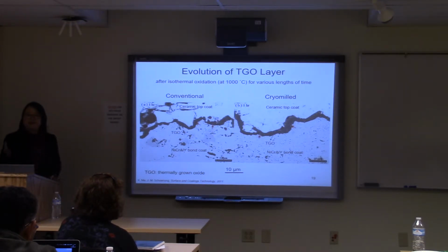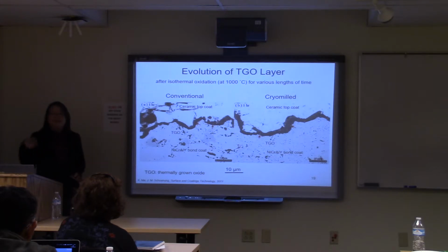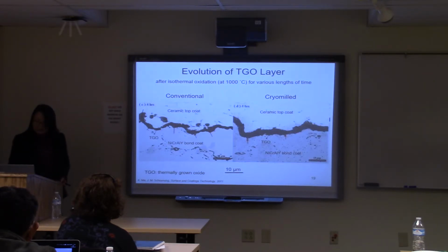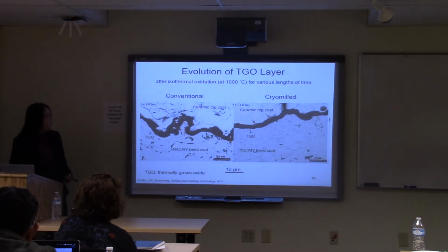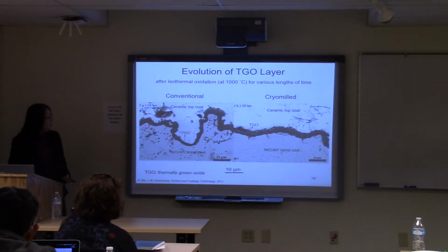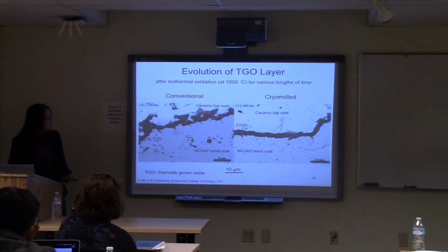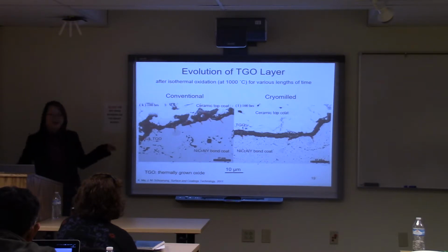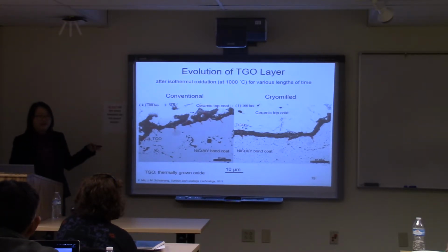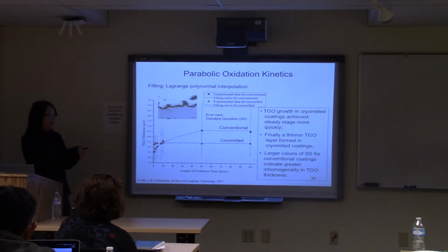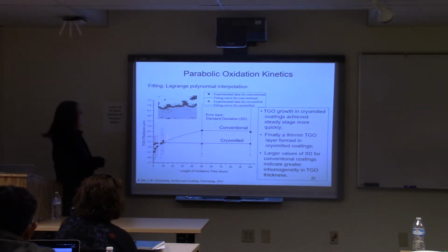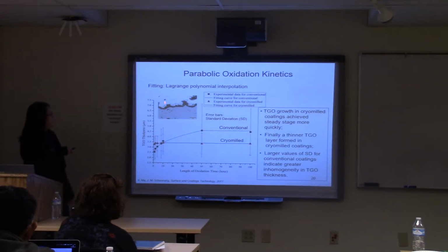That might be, from the EDS, we identify that's a secondary oxide phase instead of the alumina. So this is 1 hour, and after 4 hours, 8 hours, 10 hours, 50 hours, and 100 hours. So this gives you an idea about the thickness or the qualitative distribution of this. But I do quantify the oxidation behavior by doing statistical measurements on the thickness of the TGO here.